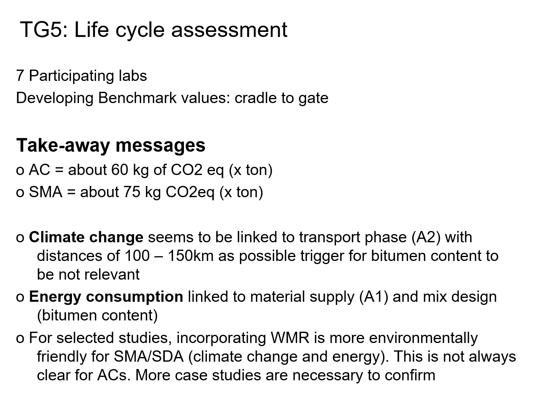TG5 looked at life cycle assessment. In this case, there were 7 participating labs. They developed benchmark values. They looked at the material from cradle to gate, and that means that the performance of these materials were not considered in their analysis. What they have seen is asphalt concrete has about 60 kilograms of CO2 per ton. And SMA, which is the stone mastic asphalt, has more CO2, about 75 kilograms of CO2 per ton.